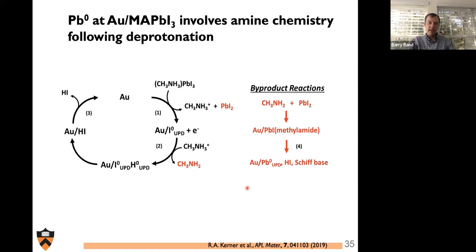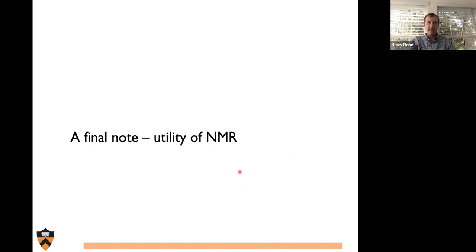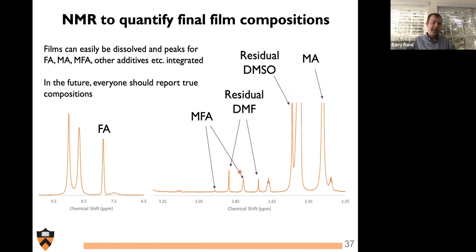So bringing it back around, these things are very relevant to solid state systems, but understanding interactions between lead and these acids like methylammonium and formamidinium in the presence of these solvents and other reactants and byproducts will allow us, I hope, to stabilize these systems. So a final note on the utility of NMR. I hope that some of these measurements like EIS and space charge limited current, that we find are so routine in the Perovskite community, can start to fade away and some other measurements take their place. One that is so simple is to use NMR to quantify your final film composition.